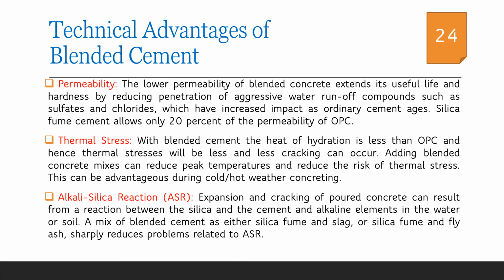Some more technical advantages are permeability, thermal stress and alkali-silica reaction. Considering the aspect of permeability, as we have discussed, blended cements are made with finely powdered pozzolanic materials. Hence, the concrete made from blended cements is more dense and the permeability values will be very low. It is observed that only 20% of the permeability of OPC is there for the pozzolanic materials.